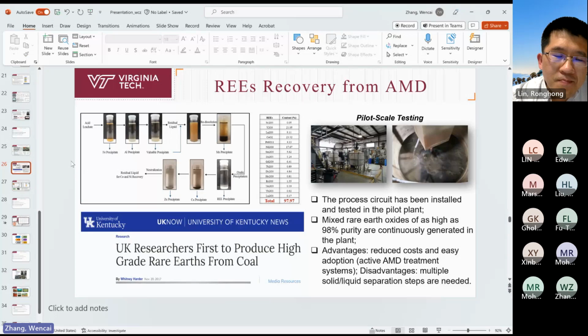So the AMD is kind of special because the rare earth concentration in AMD depends on weather, and also the rare earth content is in the host material. In most cases, actually, in the AMD, the rare earth content is less than 1 ppm, and we need to keep this in mind. It's less than 1 ppm, but there is an advantage of AMD because the mining companies need to precipitate and neutralize AMD in any way.